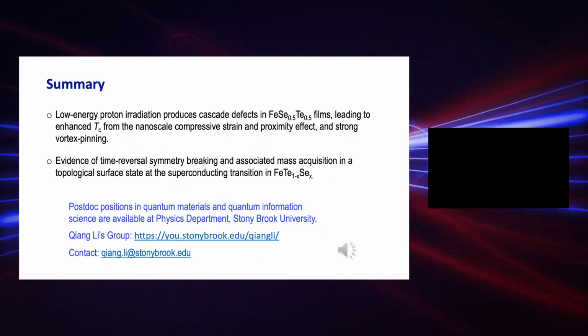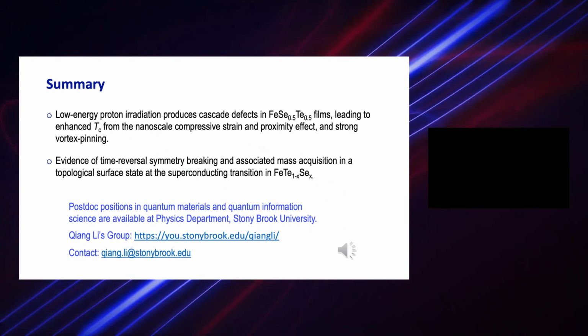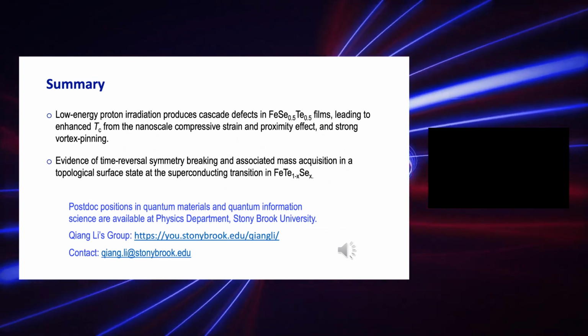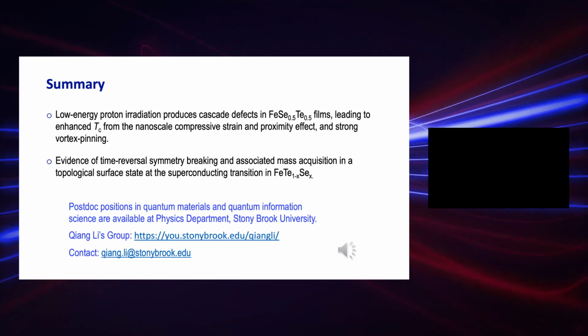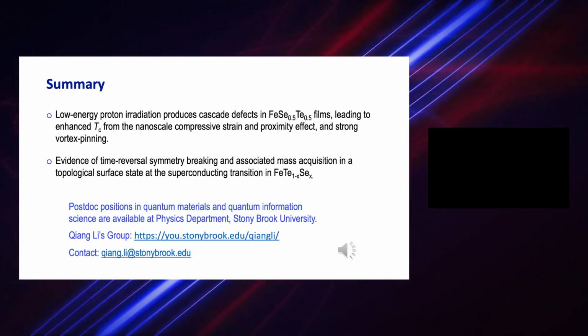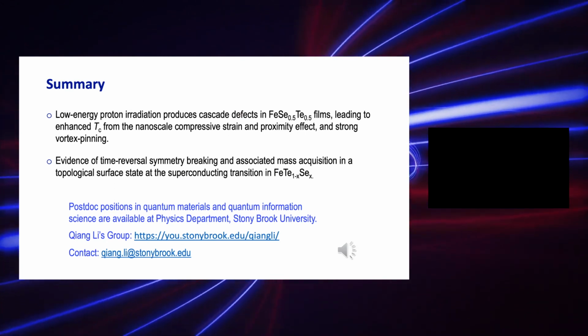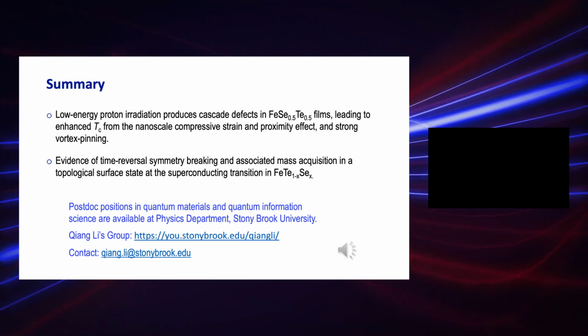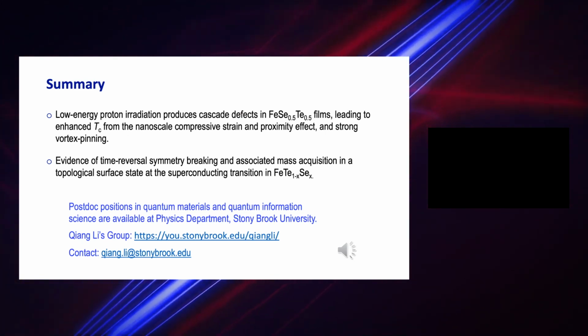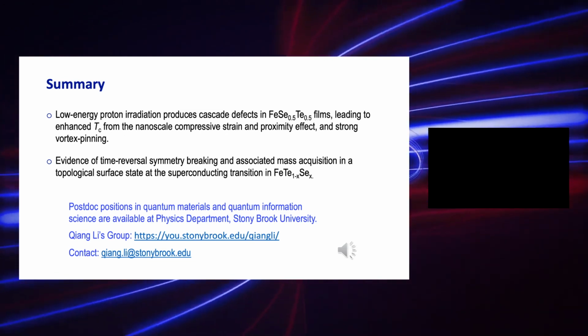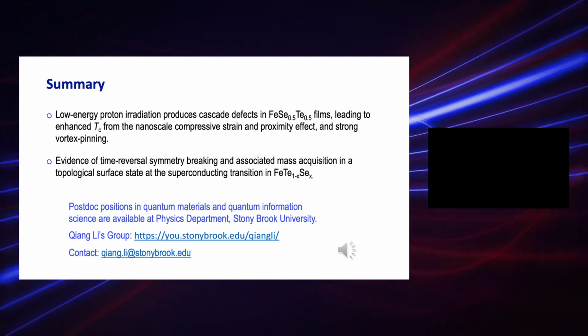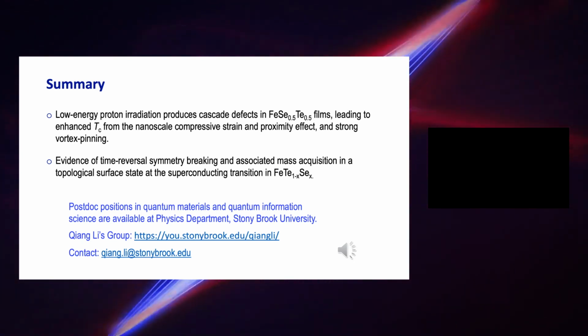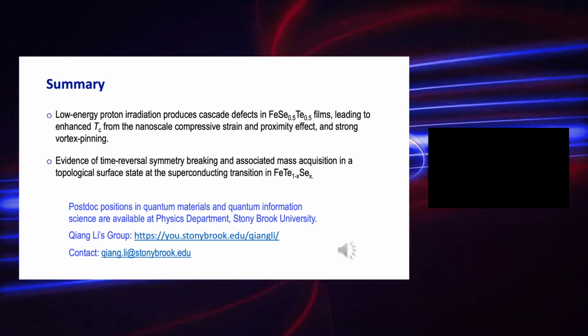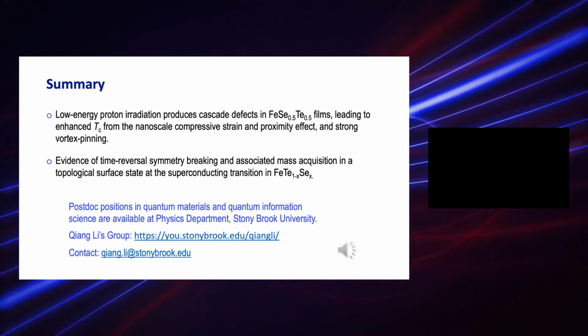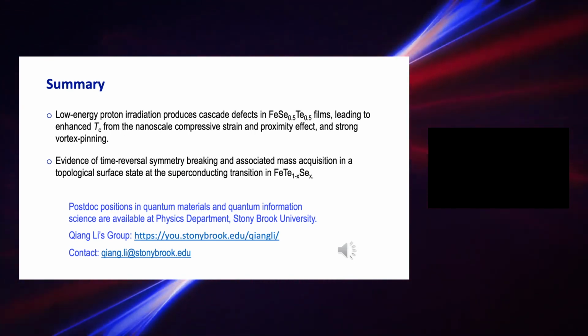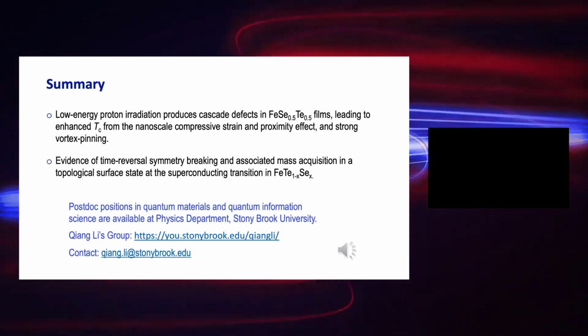Although we are a bit far away from building a practical system using iron chalcogenide superconductors for energy, high field, and quantum information science applications, I think the potential is there, and it's interesting to pursue, also for fundamental studies. So now let me summarize my talk today. I have shown that low energy proton irradiation can produce cascade defects in the iron chalcogenide films, leading to enhanced Tc from the nanoscale compressive strain and proximity effect, as well as strong pinning centers to enhance the critical current density. I also showed you the evidence of time reversal symmetry breaking and Dirac mass acquisition in the topological surface state at the superconducting transition in iron, tellurium, and selenium.